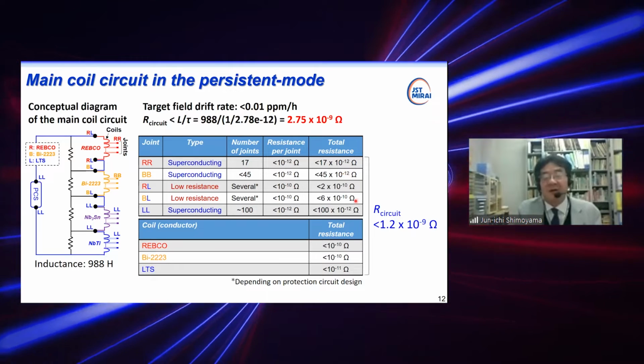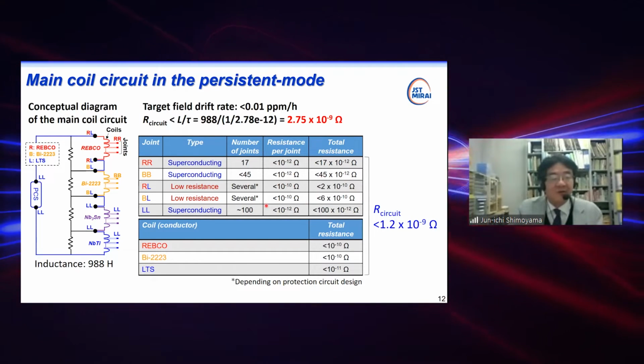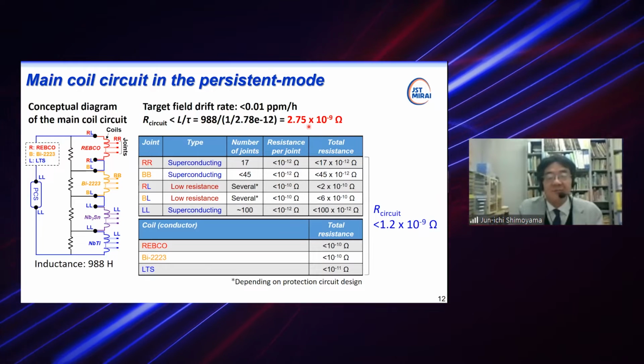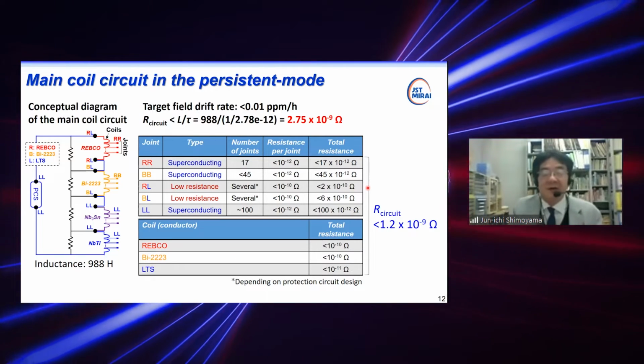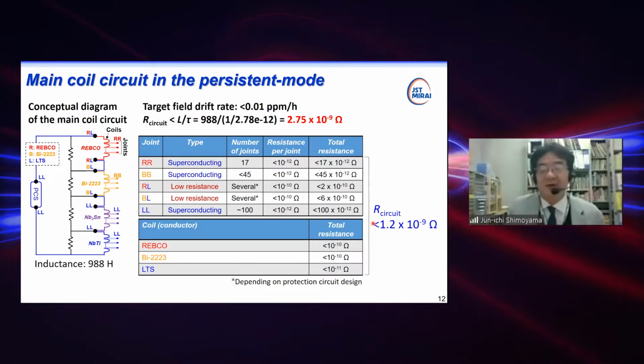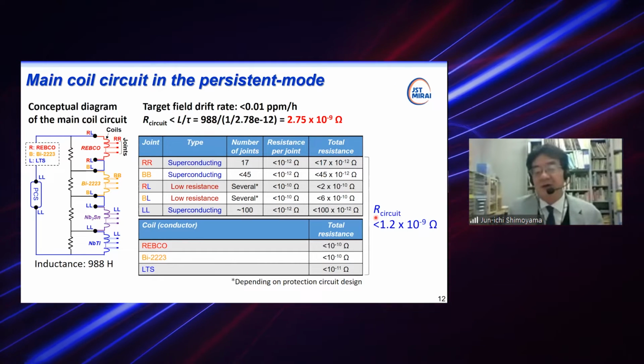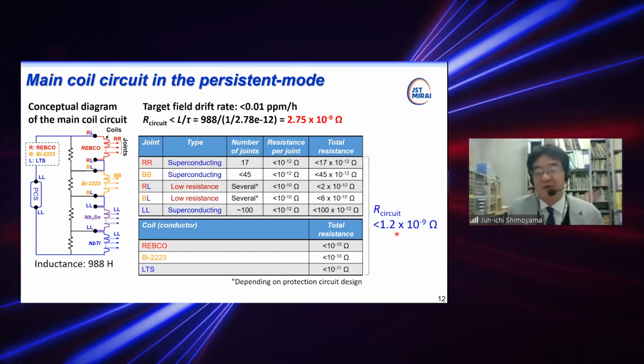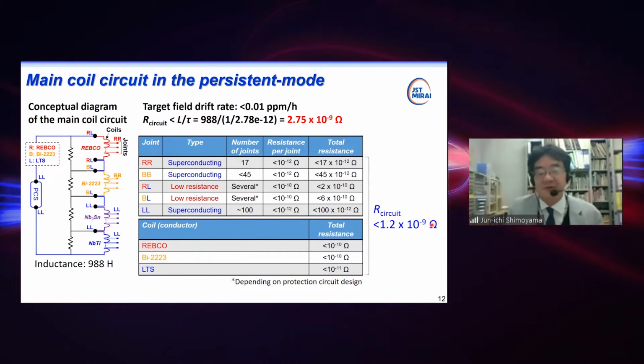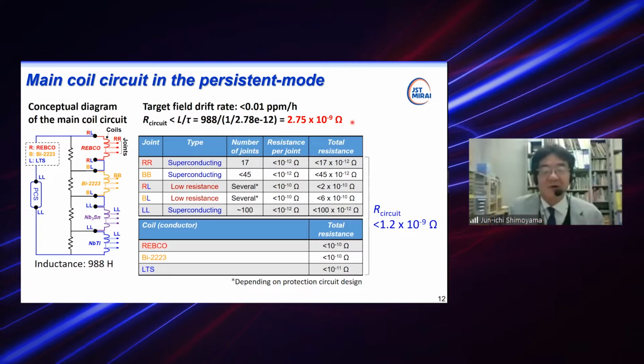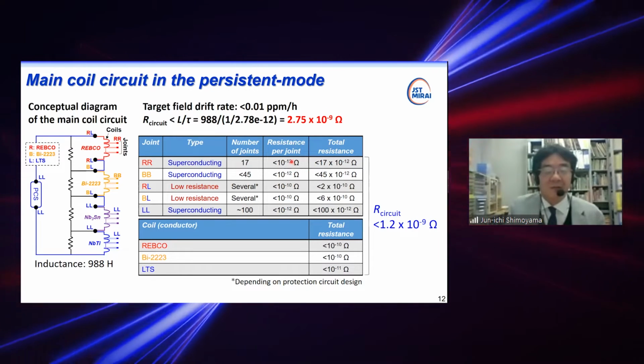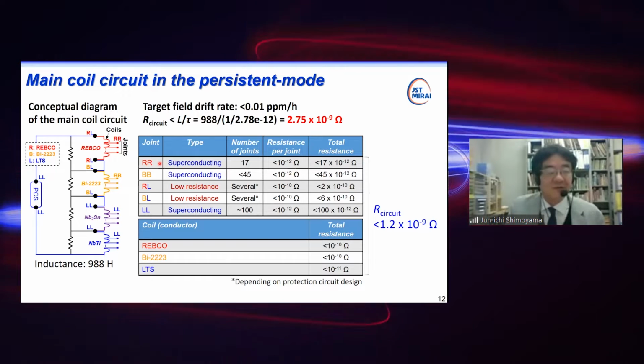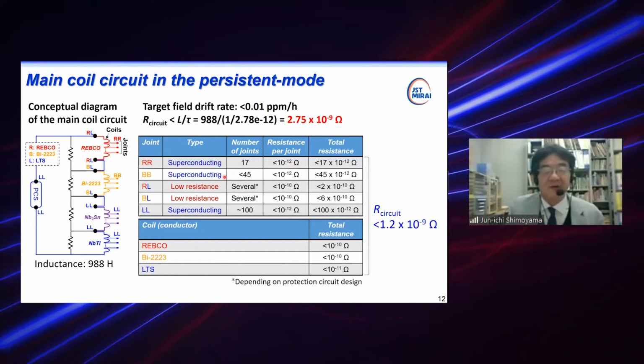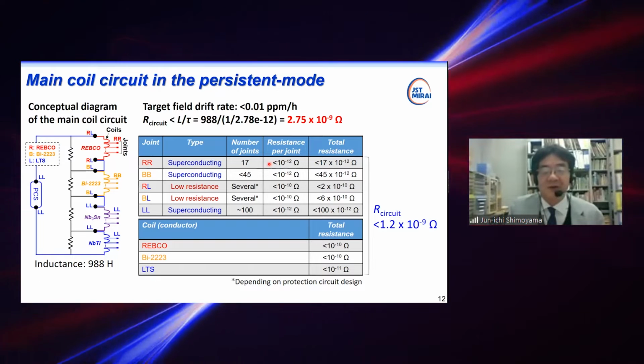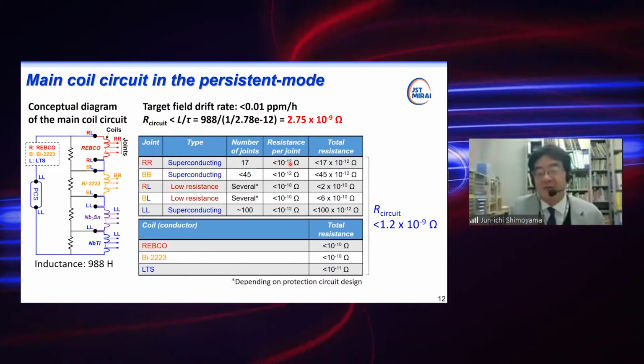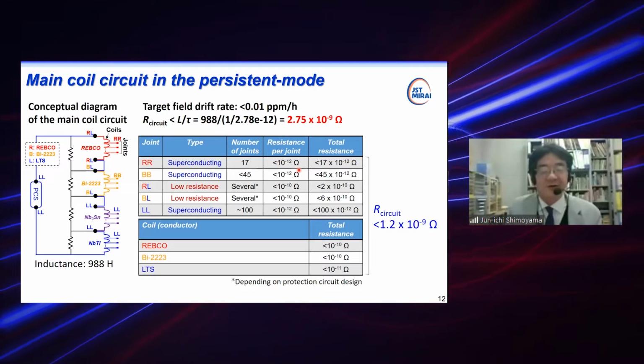Therefore, we must design the total resistance of this circuit smaller than this value. In the current design, the calculated total resistance of the big coil is less than 1.2 times 10 to the minus 9 ohms. This satisfies the requirement. Anyway, all superconducting joints connecting REBCO and Bi-2223, and Bi-2223 to Bi-2223, must satisfy very low resistance, less than 10 to the minus 12 ohms. These are very challenging values.